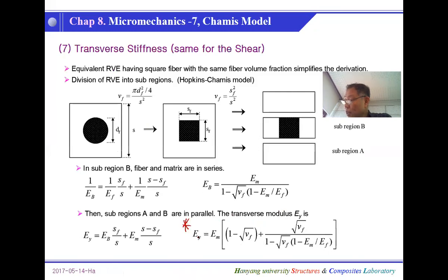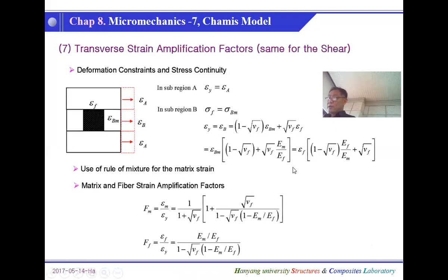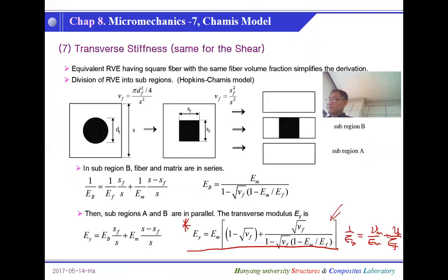Okay, this is the one you can use. You know, previously we used VM EM plus VF EF, right? And this one is more accurate. Okay, so this is some amplification factors, which is just for your reference. Just for your reference.